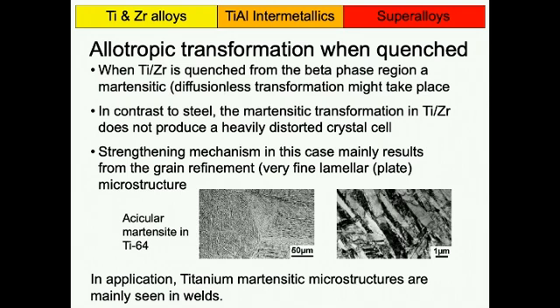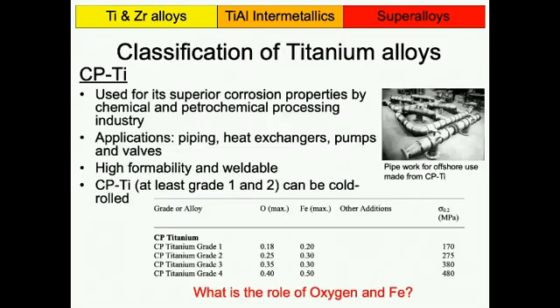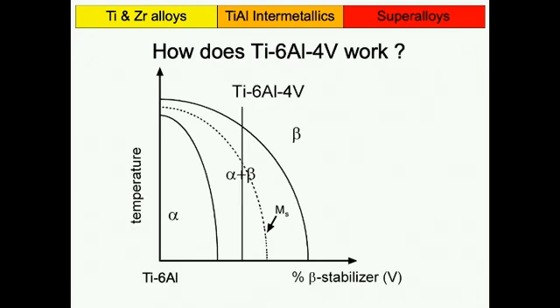If you, for instance, have high levels of carbon in steel, you probably learned that you have retained austenite in it. And here, the way it works is if you have too much beta stabilizer, you get that as well. And you might want that. Of course, I mentioned earlier near beta titanium alloys, and they actually exploit that. So we will discuss that later.